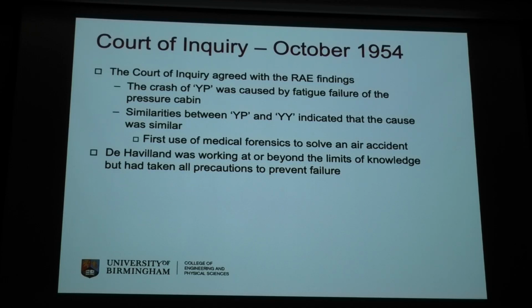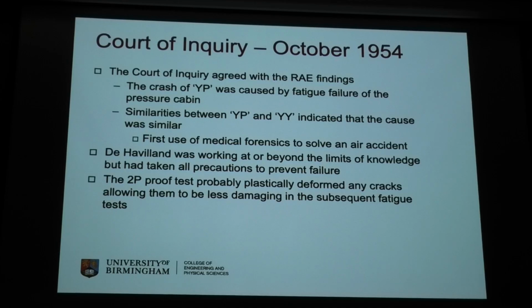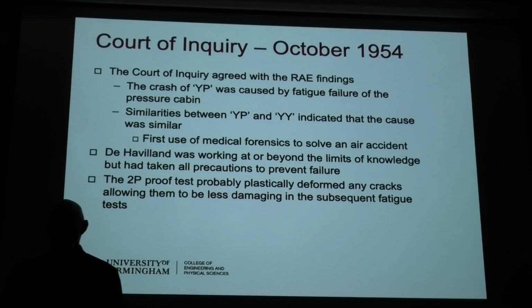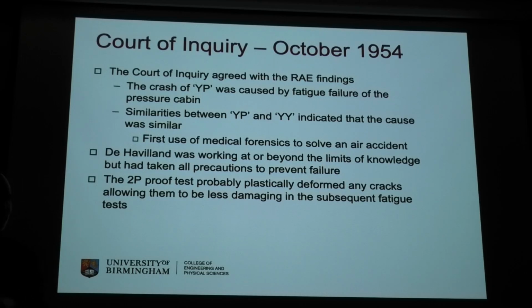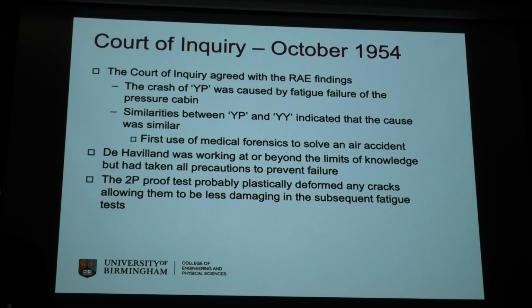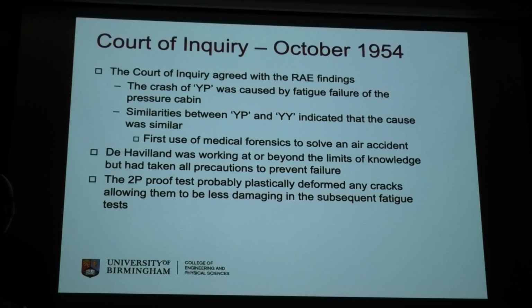Why had the nose section survived 18,000 cycles? The midsection, 16,000. There was no indication in any of the tests they'd done that this was going to happen at 2,000, 3,000 cycles. What transpires and comes out with modern knowledge is that the 2P proof test that they applied to those two sections probably took the cracks, plastically strained them, formed a strain field around them, and that actually arrested the cracks, probably for 15 to 20,000 cycles, before there was enough crack growth to go into base metal outside of that plastically deformed zone that formed a compressive stress around the crack, and prevented further fatigue. And it was purely down to the fact that they did that proof test on the two sections before they did the fatigue test.